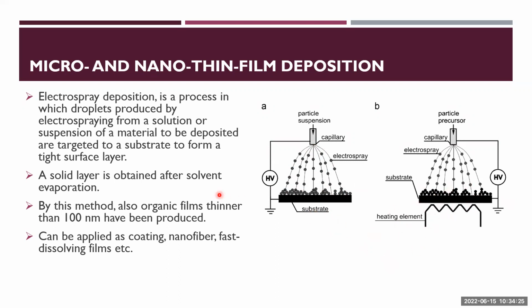So there are many applications for this. The most common one is to prepare fast dissolving films in pharmaceutical applications. You can get a film thinner than 100 nanometers. So you really can go for very, very thin films, and it's a very controlled spraying. It can also be used for some kinds of coating, but it's really very controlled, and you can go for very, very thin coating.